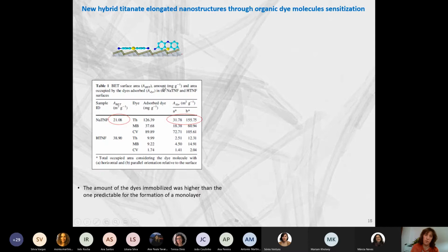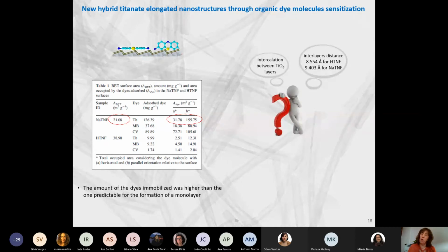We have all of our molecules in a flat position or in a perpendicular position in relation to the surface. And after some measurements and some calculations, we can see here that, for instance, for thionine, our material is a nanofiber, so the surface is not so big. To have all these molecules only on the surface, we need an area that we don't have. So this tells us that we don't have only adsorption, or if we have it, we don't have a monolayer formation. We have a multilayer. But we decided to think about the possibility of these species, because they are a kind of planar molecules.